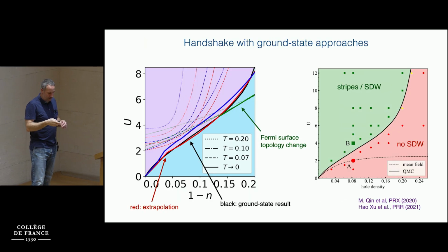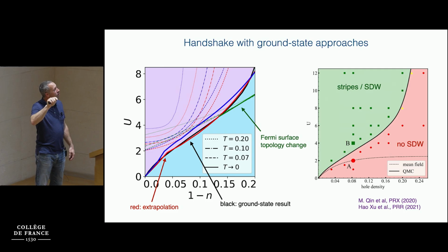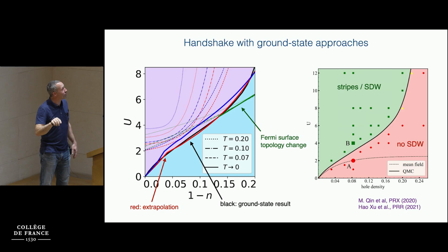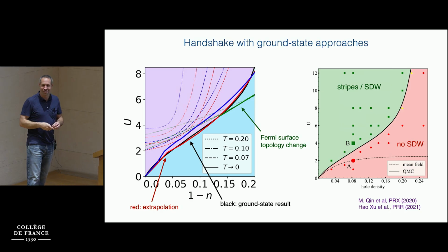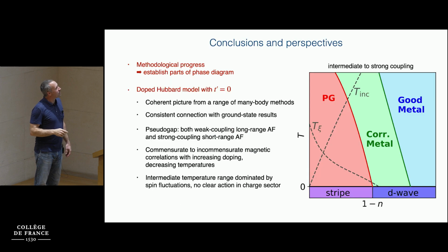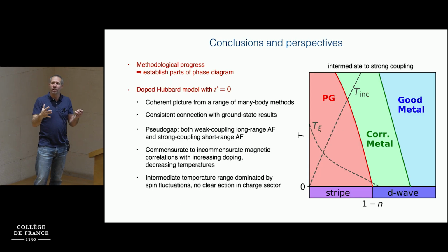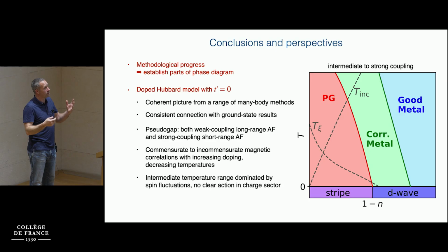And what we find, quite surprisingly, it's very striking, is that our extrapolation at T equals 0 in the U-doping plane, and this red line is the extrapolation of the pseudogap regime, matches very closely to the line found in zero temperature methods that separates the stripe phase from the non-stripe phase. Actually, the line here is the black line. It's almost on top, and I want to emphasize that we found this red curve before we had the black data. So this was actually an honest extrapolation. Great, so this seems to be saying that as we decrease temperature, eventually the pseudogap regime becomes unstable and turns into a stripe state at zero temperature.